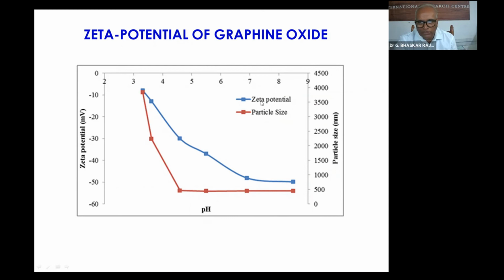Similarly, if you look at the zeta potential with reference to the particle size, the smaller the particle size, the greater the zeta potential. When particles become bigger, it changes a little, but in any of these zeta potential measurements, the particle size should be within, say, 10 to 20 microns. Beyond that, the particles settle in the tube. So we have to invariably measure particles below the 10 micron range.